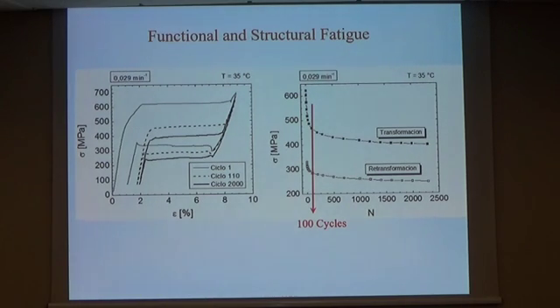Just to remember the difference between functional and structural fatigue. Functional fatigue takes place mainly in the first 100 cycles, though it continues a little, and it produces a drop in the transformation stresses. Structural fatigue takes place later and is related to the intrinsic resistance of the material. This difference is important for our proposal.